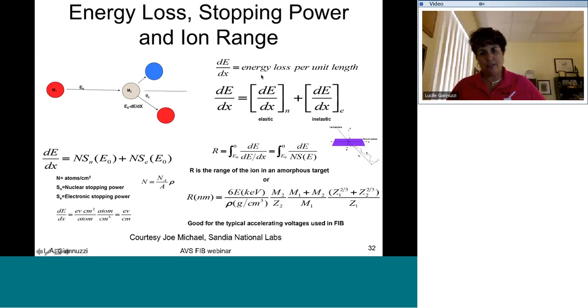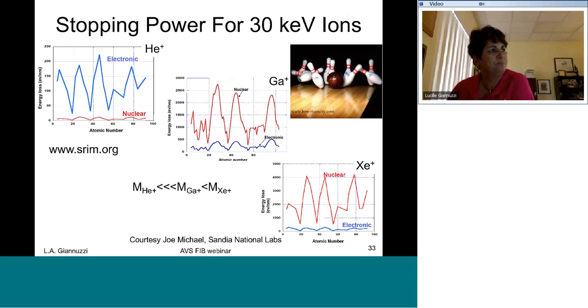So we can then take this energy loss per unit length and determine what our range of the ions are going to be, okay? And we can also determine which part of this effect is nuclear stopping power. Here's my nuclear stopping right there. There's my electronic. So we can determine what the range is if we just substitute in the masses and the atomic numbers of the target and incoming ion respectively, okay? And this is good for the typical accelerating voltages that are used in FIB.